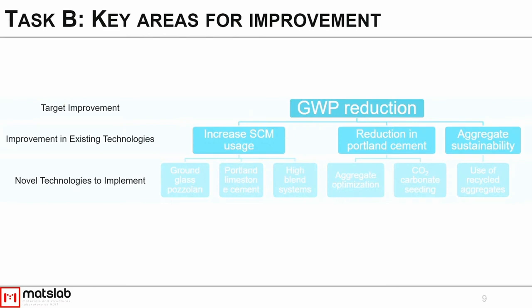We also looked at optimizing our mixtures to reduce the total Portland cement in the mixture, so improving the amount of aggregate in the system, and also looking at CO2 carbonate seeding in the system. And then we also looked at using recycled aggregates as well.